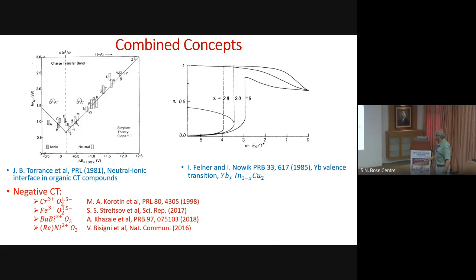This is completely different. Heavy fermions. What I'm plotting is from an extremely famous paper. It was a brief report which became extremely famous, probably a PRL reject. This is the probability of having ytterbium in the valence 3 plus, and this is the valence 2 plus, and the integer valence jump is occurring as 1 over T. This is an experimental plot. So these two are unrelated. There is no overlap between this field and this field, but they're actually the same phenomenon.